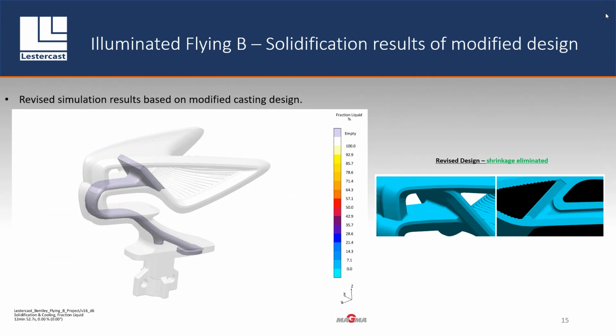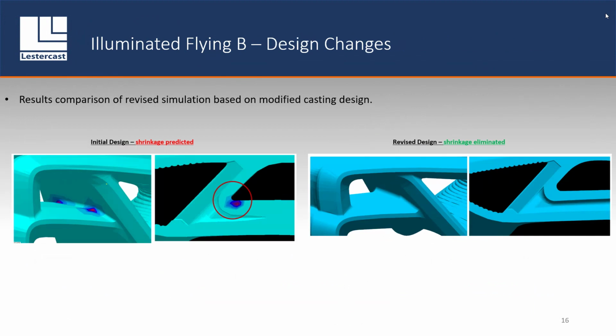Bentley were very pleased. I think Lestercast were very pleased as well. It was an issue that had been around for a long time, causing them some problems out in the field. So that was resolved. Again, you can see it before and after here. On the face of it, it doesn't look like a massive change, but we're talking very specific solidification around this area, and obviously we needed to change that. So that was successful, and that resolved one of the major problems, really.